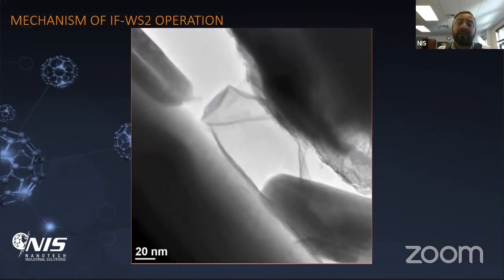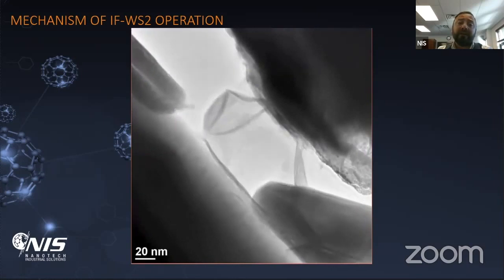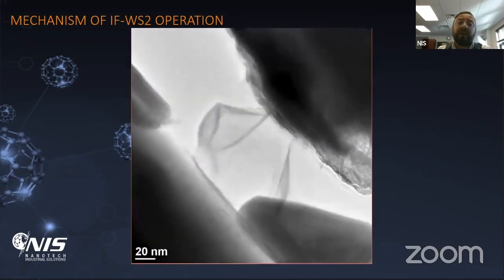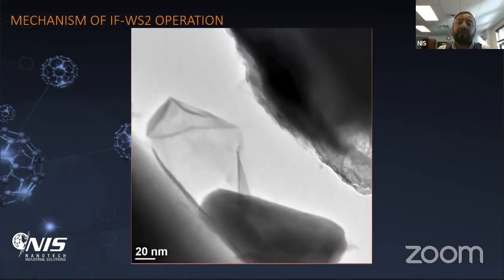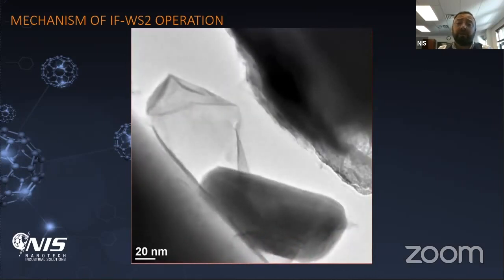But the layers that you now see on the screen are quite tacky, and it's your tungsten disulfide. It's very strong. So it creates a protective film on the surface of the metal, reducing wear and increasing wear resistance of that layer on the metal. And this particle is again ready for another cycle of exfoliation, because this particle has between 18 to 30 layers of tungsten disulfide. So it's getting consumed, but that's what you actually want, because you want to create more and more of these protective layers in your system.